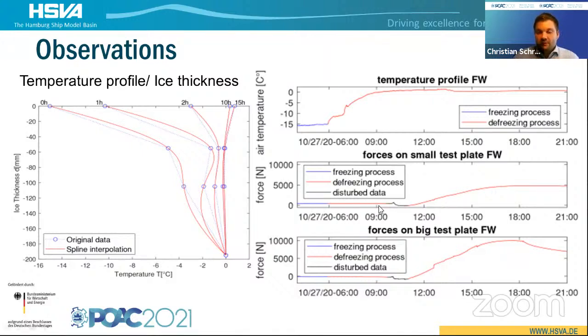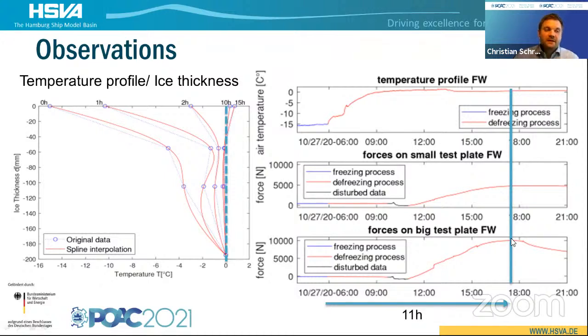And you can see on the force level, we removed some of the ice which was left behind the load scales or behind the measurement structure, at something about 10 o'clock. And afterwards, the ice got warmer and warmer. You can see it here on the left-hand side, so that after 4 or 5 hours, the ice also in the inner part went warmer, so the forces in the load sensors went up. So until about 11 hours, we reached the maximum force level due to the ice pressure on the sensors. So we measured about 10,000 newtons, so 10 kilonewtons on the big plate, and about 5 kilonewtons on the smaller test plate.